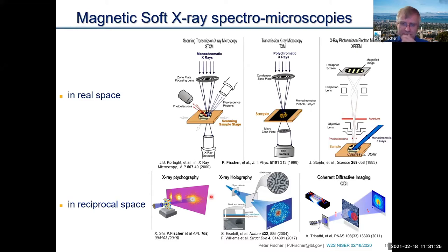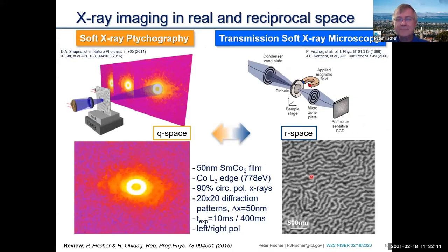And then quite recently, people really got interested in using, again, the coherence to not do real space imaging, but what we call reciprocal space imaging. So we basically go into q-space, into diffraction mode of imaging. And there's, of course, a couple of techniques: the coherent diffractive imaging technique, X-ray holography can be considered as one of them, and also X-ray ptychography, which is basically a scanning transmission X-ray microscope, but now instead of just taking point by point, measuring, let's say, transmission or fluorescence or emitted electrons and then raster scanning across the sample, you take for each of the scanning points a full diffraction pattern, and then you analyze the data and put them in a kind of retrieval algorithm to finally, and this is what I want to show you in this slide here, get a real space image of the spin texture, but with even increased spatial resolution.